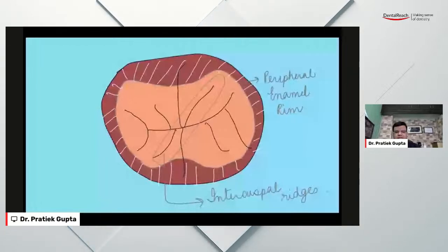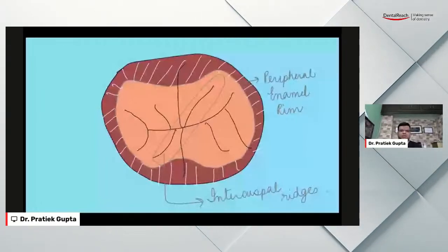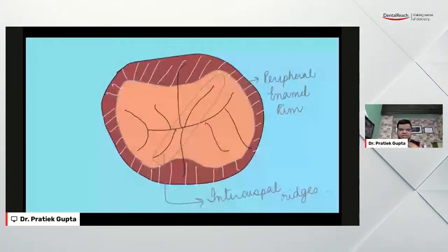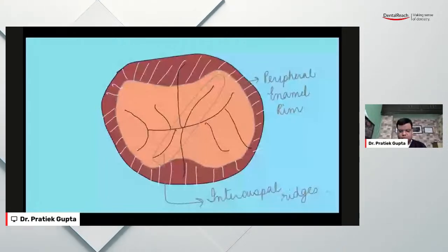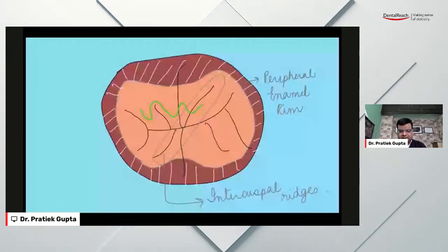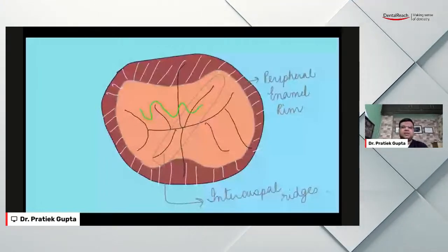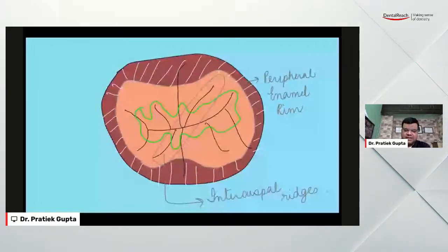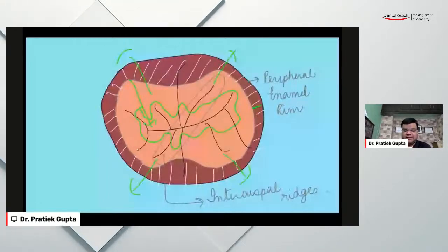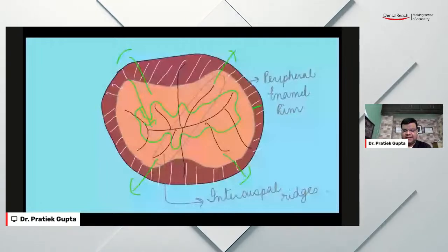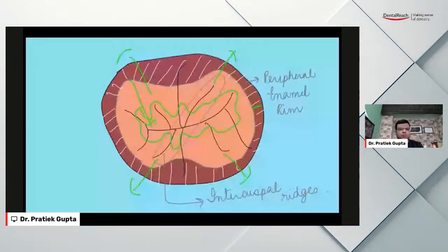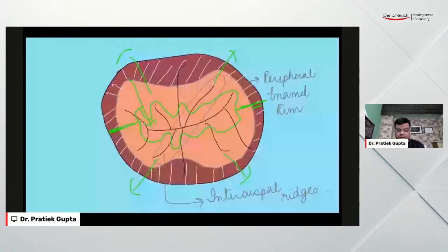Just run through this, and if you understand that the two most important structures in the human mouth, especially with the tooth, are the peripheral enamel rim, because enamel, and then the intercuspal ridges. Every time you did a class 1 amalgam restoration, you would take away these intercuspal ridges, make it a part of your restoration, and call it extension for prevention. It did not prevent anything, because now when the patient bites on this, these cusps start to flex individually. Because of this flexure, you would develop cracks along the cavity lines, and eventually you have a vertical root fracture and the tooth goes into the deathbed.